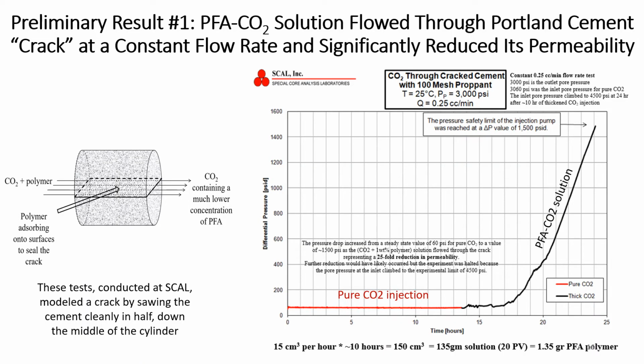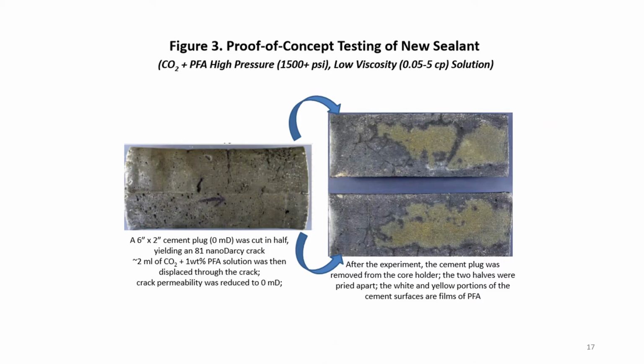Initial tests were promising. When the PFA CO2 solution was flowed through a Portland cement core, over time, the pressure drop to keep a constant flow rate increased dramatically. After the test, we had to pry it apart and found that there was a white and yellow film on the cement, which was the PFA.